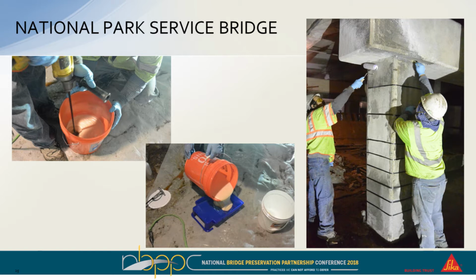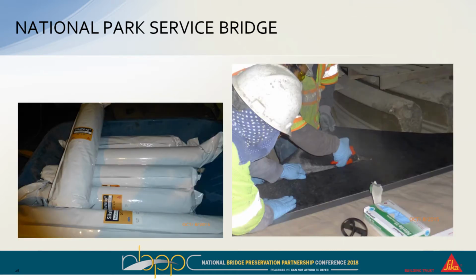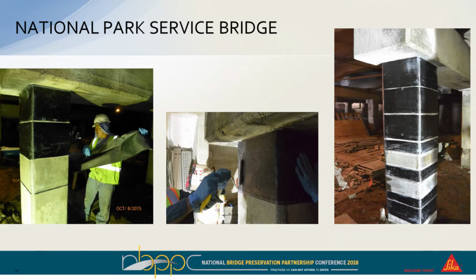Here's the FRP that was applied in the bags. The contractor is literally just cutting them into strips and then wrapping it around the column. Again, you can see the workforce on each column is only about 1 to 2 people because it's a very simple process, wrapping it and then just using some type of fiberglass rib roller to smooth it out.